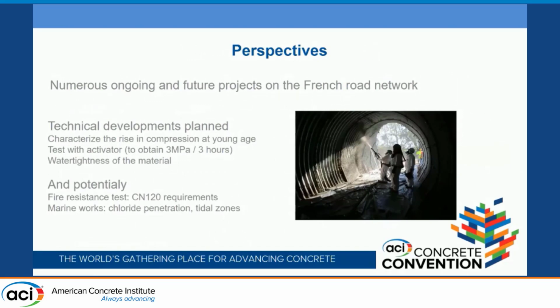Several new developments are planned. We expect to characterize the strength rise at a young age. For this, tests with an activator to obtain 3 MPa at 3 hours are to be planned. The characterization of the water tightness of the sprayed UHPC thin shell could also be useful in underground works. Other specific characterizations could be developed later.